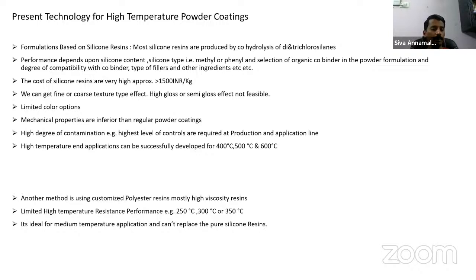Second, we believe that we supply HR powder, the customer sprays, and they get heat resistant performance. Actually, this is how we perceive it: powder is produced with silicone resin, we supply, the customer sprays, and they get this performance. Actually, it is not so. The customer has to do grit blasting, then they need to go for aluminum metallizing. Unless aluminum metallizing is done, you will not get the required protection, particularly against corrosion. You will not get corrosion protection. So aluminum metallizing is also an additional cost. Then powder coating is applied.